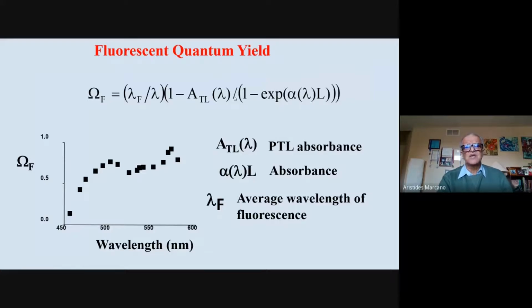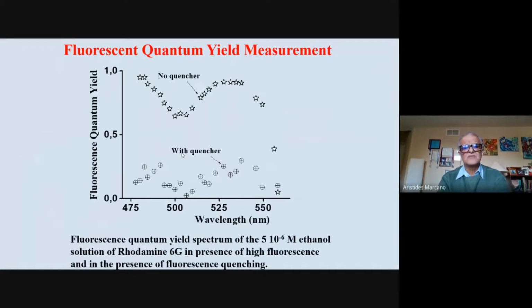You can estimate the fluorescence quantum yield of this experiment just using this relation between the thermal lensing and the total absorption. Alpha is the total absorption, and this is the absorption measured by the thermal lensing. When you do that, you can obtain the fluorescence quantum yield, which is a number that says the ability of that particular sample to produce fluorescence.